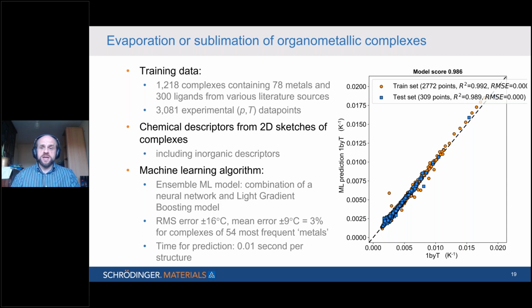And you can see the results in the graph. So this is a correlation graph of the experimental data on the x-axis, the reciprocal of the evaporation temperature, and the predicted evaporation temperature on the y-axis, again, the reciprocal. We trained against 80% of the data, and that's shown in orange. And then we reserved 20% of the data as a test set, which the model hadn't seen before, and checked to see how well the correlation was for that unknown set. And you can see that the results are really very good.